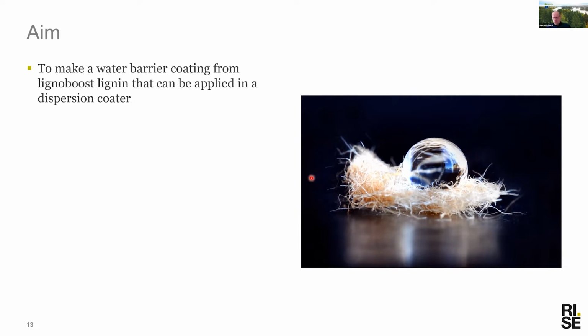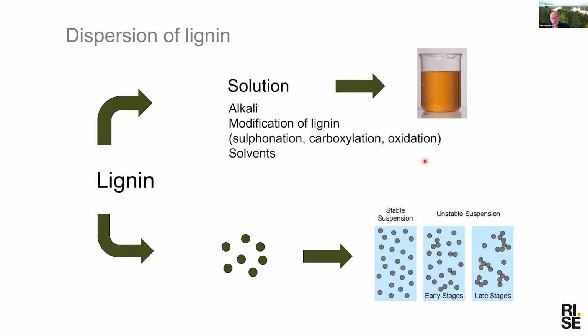And this is really where we come into the concept that we have developed. We want to get something like this, where you have a water repellent surface, but we should apply it in a water-based system, which is quite tricky. When it comes to lignin, you either dissolve it in alkali, or you can modify it by sulfonation, carboxylation, and oxidation. And Pedram, who is talking afterwards, can tell you all about these modifications. You can also use solvents. With the first two, you potentially lose some of the hydrophobic properties of the lignin, so that makes it a little bit hard to do. Solvents, I'll get back to that one later on.